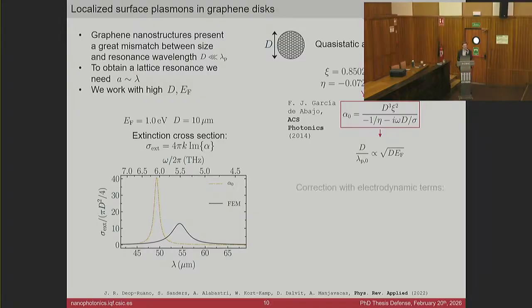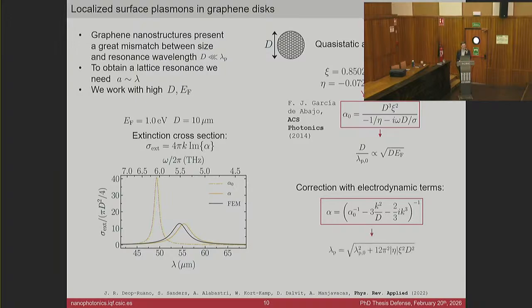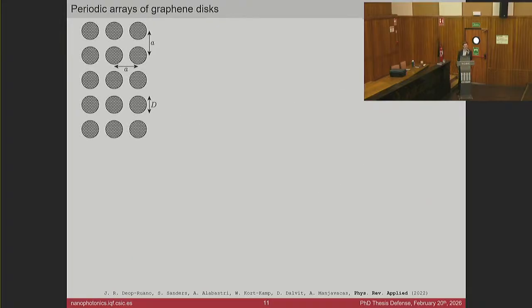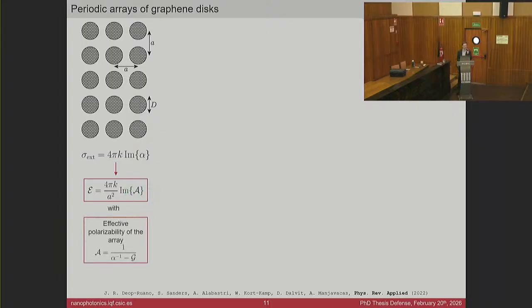So to improve our model, we have to introduce some electrodynamic corrections that we can see here. We can see that now there is a much better result, and we can even derive analytically the redshift of the resonance that we see from the quasi-static model to these electrodynamic corrections. Let's move to the actual array. What we are looking for is lattice resonance in a periodic array of graphene nanostructures. So let's generalize our extinction cross-section by the definition of the extinction efficiency, in which now the polarizability of the nanostructure has been substituted by the effective polarizability of the array, including, as we saw before, the individual polarizability and the lattice sum, the interaction.